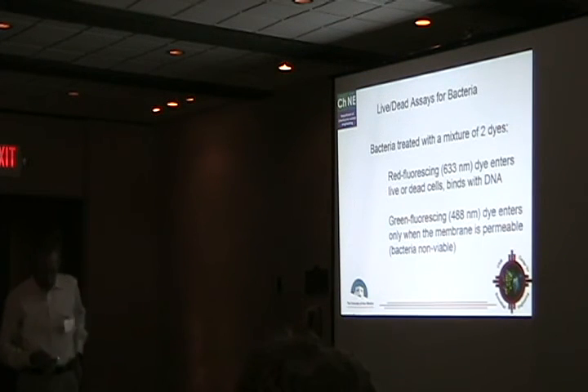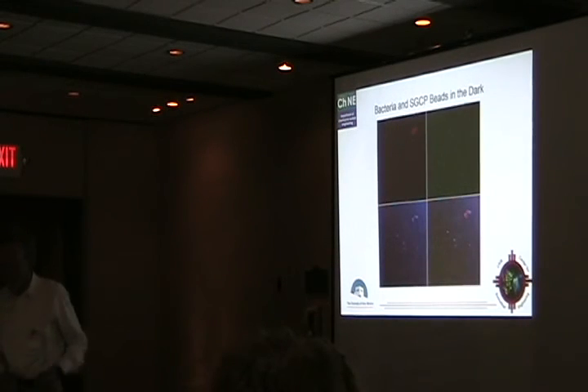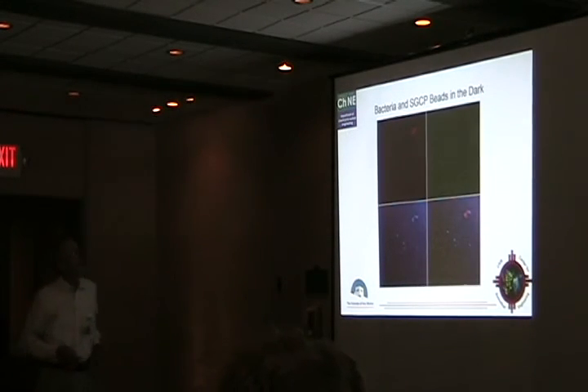And we've both cultured the bacteria, but we've also used what are called live dead assays, where we treat the bacteria with a mixture of 2 dyes. There's a red fluorescing dye, which can get into either live or dead bacteria and bind with the DNA. And there's a green fluorescing dye that we're using that enters only when the membrane is permeable. In other words, the bacteria are non-viable. And the results are really quite nice.